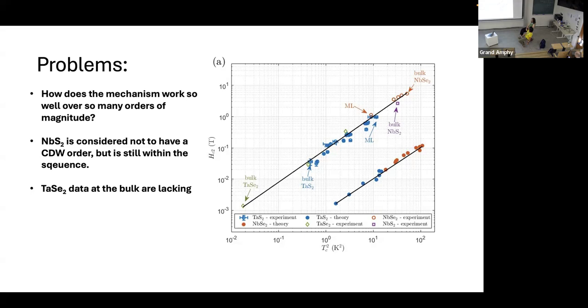Another problem that we have is tantalum selenide. There's very little data on tantalum selenide. How can you explain superconductivity degrading so strongly? People use tantalum selenide as a contact because it's supposed to be a metal. But you have this ancient paper showing that it's actually a superconductor, but with a very low Hc and very small Hc2. So how does tantalum selenide really behave? It gives you such a wide range of superconductivity.